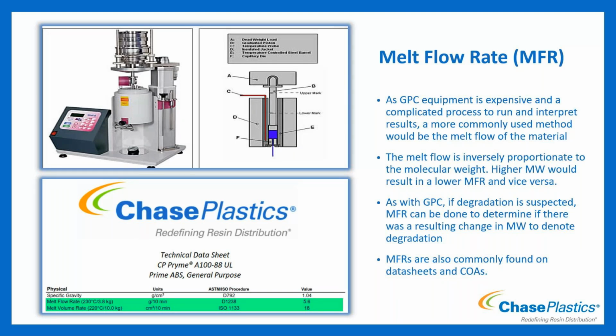As you might see, they are commonly found on data sheets, so we have a general idea of where it should be. So in the case of our CP Pryme A100-88 ABS, it has a melt flow of 5.6. If suddenly it decreases or increases based on the molecular weight, so if we degrade it greatly and the molecular weight decreases, our flow would greatly increase. So if we were to test it and somehow we tested at 15 or 20 melt, we've severely degraded that material because we're breaking it up. It's flowing so much easier now because we have messed with the molecular weight. And so could be a way to test that as well.